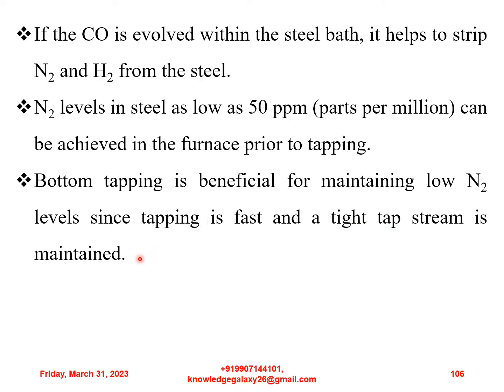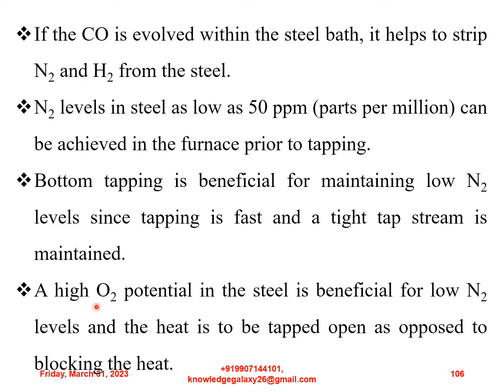Bottom tapping is beneficial for maintaining low nitrogen levels since tapping is fast and a tight tap stream is maintained. A high oxygen potential in the steel is beneficial for low nitrogen levels, and the heat is to be tapped open as opposed to blocking the heat.